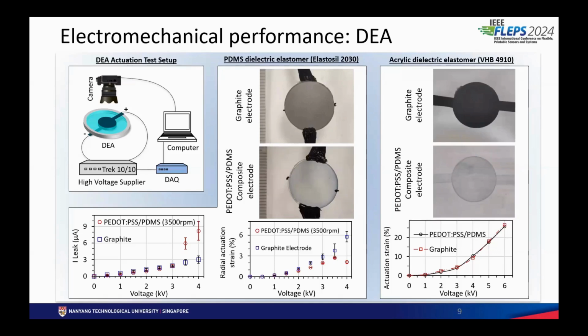As you can see here, this is a device made on the 20 micron PDMS. We found that because of the seepage of the PEDOT:PSS on the very thin PDMS layer, it increases the leakage current when applied voltage is above 3.5 kilovolts. However, while trying it out on a thicker film, here VHB 4910 is a 1 mm thick acrylic double-sided tape, so when pre-stretched, it is around 200 microns, we found that the actuation strain is quite comparable to the conventional graphite electrode. So we can conclude that for a reasonably thick film, there is not much compromise we need to make.